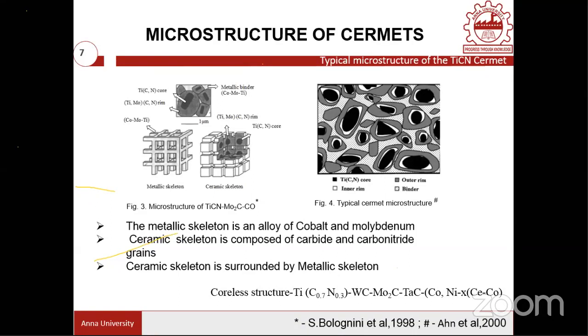The metallic skeleton is your binder, in which you have the solution, which is the inner rim, and inside you have some hard material. Basically the TiCN is a core, which is the harder material, and the inner rim is a solid solution which will have both toughness as well as hardness. But compared to TiCN, the hardness value would be lower here. Then you have a metallic material surrounding these spaces, which has really good toughness. Therefore, depending on these three important parameters, the hardness and toughness of this material would change. So you can tailor make this material by modifying the microstructure, modifying the hardness as well as the toughness value. We are going to play with this kind of mechanism in the future.